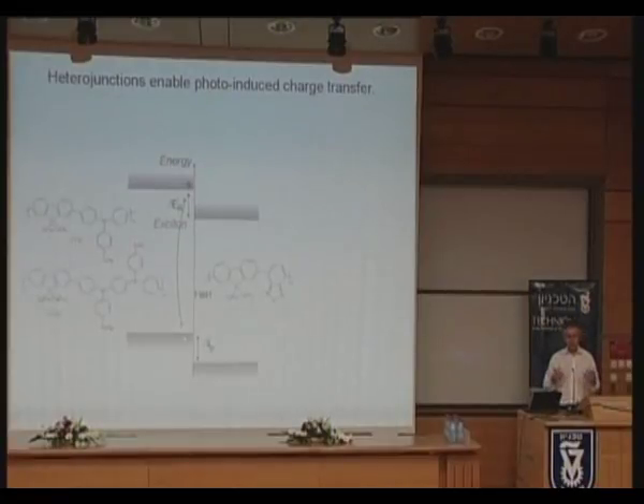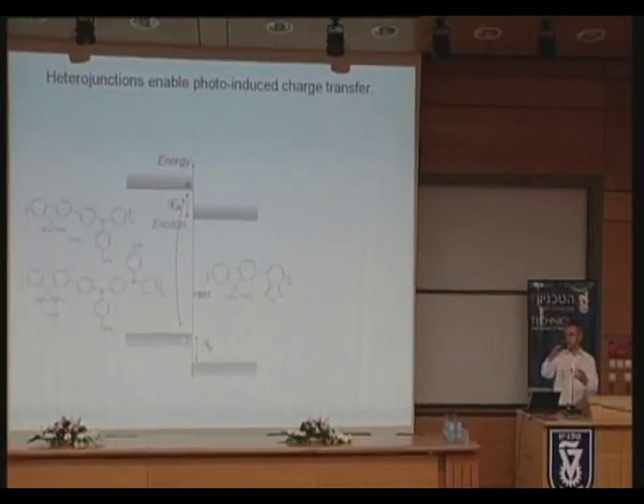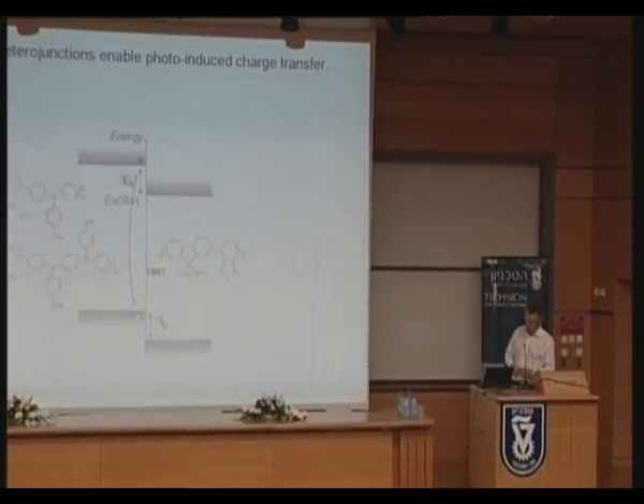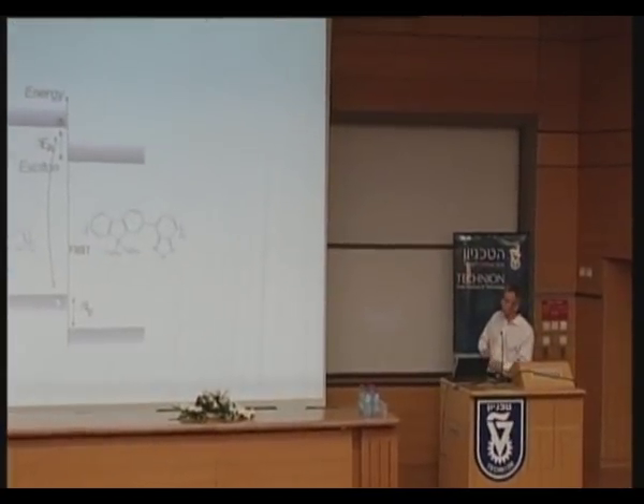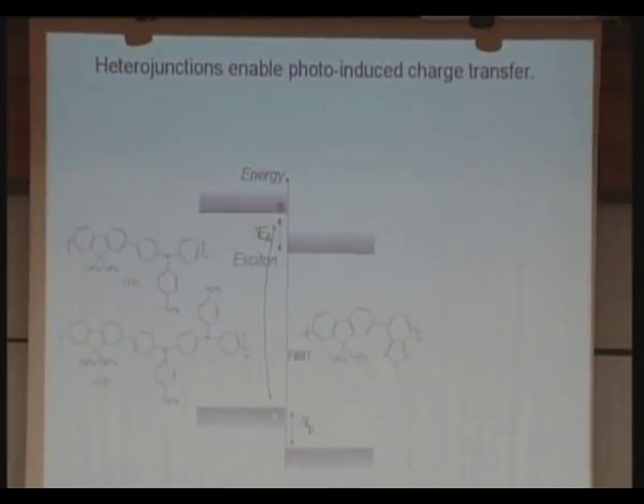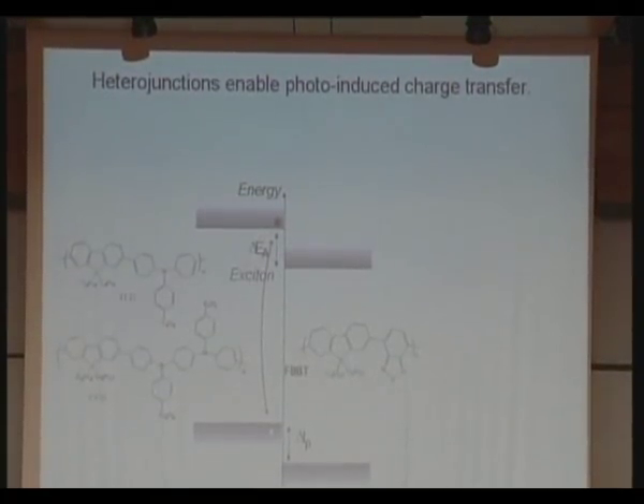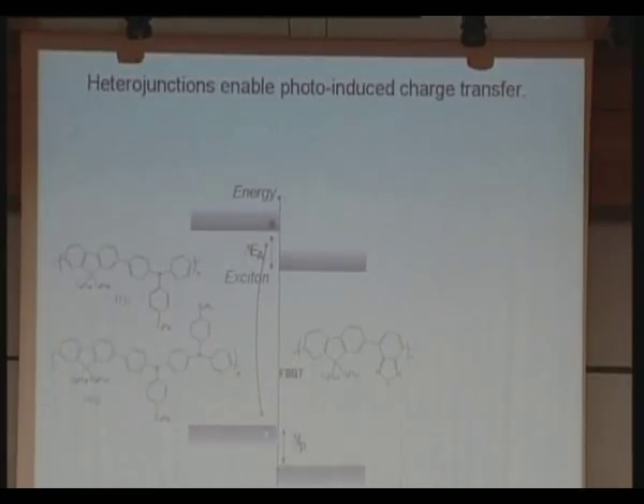And the limiting step is actually close back to the problem of Coulomb interactions, poor screening. It's the problem of screening of the charge-separated state we get across the heterojunction when we first photo-excite. And some particular material systems, and the details don't matter so much, give us a clue as to what's going on. And they're shown here. This particular polymer, F8BT, has this benzothiadiazole unit in it, which is a strong electron acceptor. That, if you like, is the replacement for the cyano groups I showed you previously. And these polymers on the left, PFB and TFB, have a nitrogen with three phenyls around the nitrogen. Triphenylamine is a good hole acceptor.